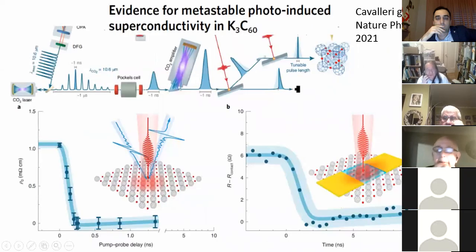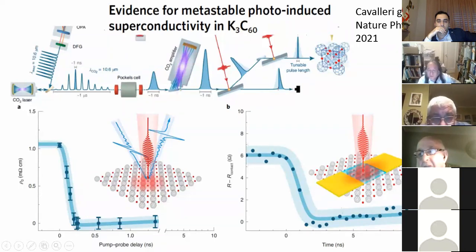And this is possibly very important, because very recently this group in Hamburg developed a new and stronger way of excitation. This red light now comes with a longer pulse. And surprisingly, what they observed is that this transient superconducting state becomes long-lived. It used to be 20 picoseconds or something in the previous graph, but now they are successful in maintaining it to 1 nanosecond or 5 nanoseconds or so on. And they now can measure this with transport, just like a resistivity measurement, and show that resistivity is nearly 0 even 5 nanoseconds after the pulse excitation. So this is showing that this laser excitation may really be making systems superconducting.